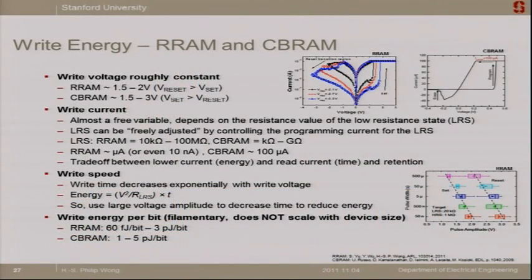The write speed is interesting also for both of these things. The write time decreases exponentially with the write voltage. This experimental data shows the write pulse width versus the write pulse amplitude, a voltage-time relationship. It goes exponentially. So if you increase the voltage, then you would decrease the write time exponentially.